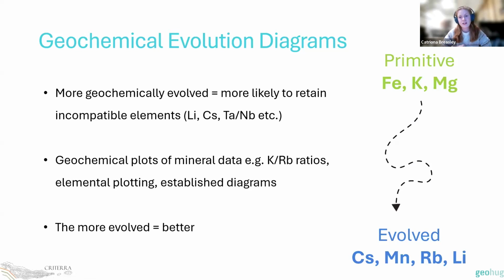So geochemical evolution is very important for understanding pegmatite systems because essentially the more geochemically evolved your melt is, the more likely you are to retain your incompatible elements. So when you have an igneous intrusive body crystallizing, typically the elements that you're going to crystallize out first really like fitting into crystal structures. So this can be iron, potassium, magnesium, to name a few. And then essentially your system concentrates your incompatible elements that have either a weird size or a weird charge balance in the elements themselves.